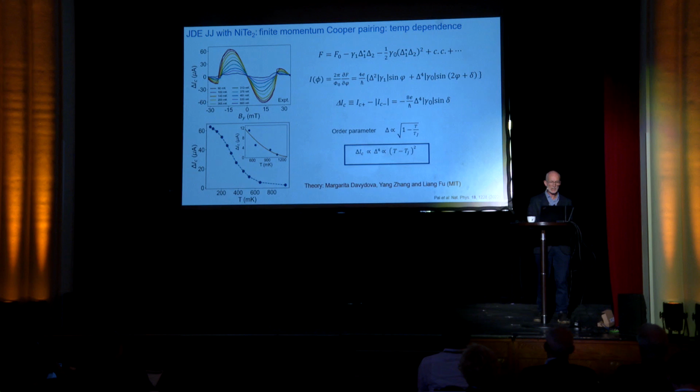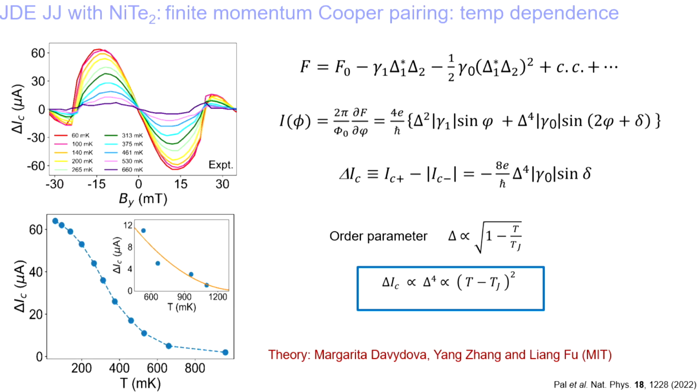Moreover, we can predict how the critical current difference for plus and minus currents, zero in zero applied field, increases with the field perpendicular to the current flow, then to a maximum value, decreases, crosses zero, and we have this fantastic oscillatory dependence of the diode effect as a function of these magnetic fields. And the magnetic field basically introduces a Zeeman splitting to the band structure through these topological surface states, we believe.